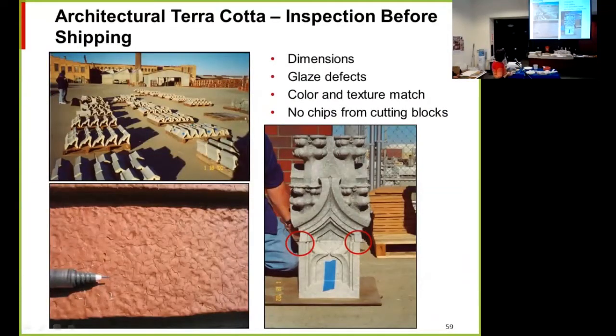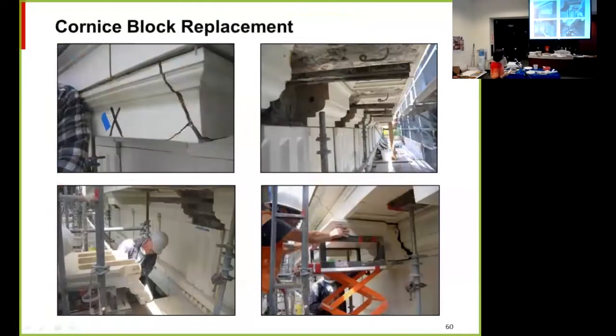A lot of times we will go up to the plant, this is Gladding McBean, and check the terracotta before it's packed up and shipped. Some of the things that you're checking are the dimensions of it, so blocks should line up with each other. Checking for glaze defects, you don't want to see little cracks or crazing. Make sure the color match and the texture match is good. And then a lot of blocks nowadays are extruded and then saw cut. And you want to make sure that in doing the saw cutting, the glaze is not chipped.